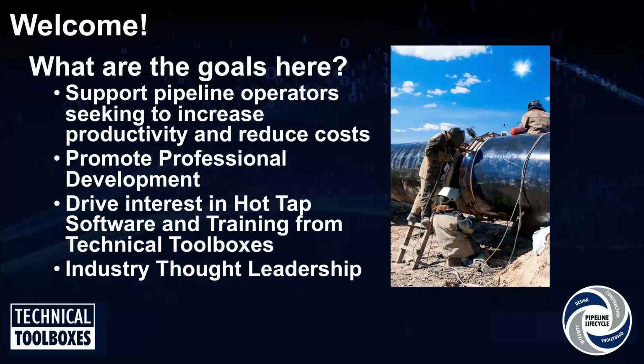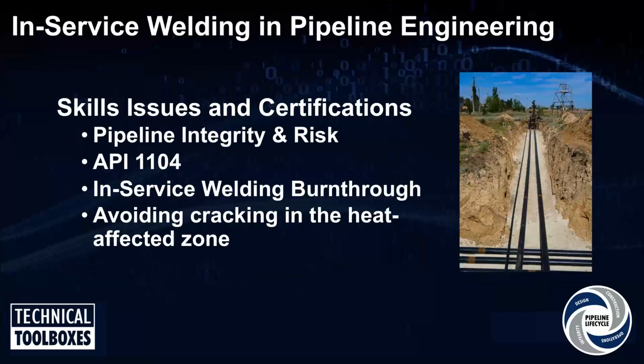So the code defined in API 1104 covers hot tapping and welding in in-service pipelines. During that process, burn-through can cause hydrocarbons in the pipeline to escape or ignite during the procedure, leading to spills or injuring workers. After, welded areas may be weakened by hydrogen cracking in heat-affected zones. You need to be able to address these challenges with accurate calculations and minimize your risk.